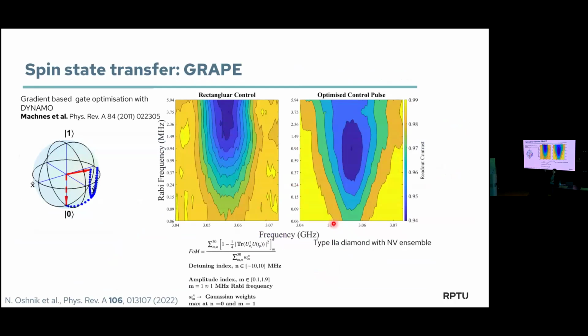So normally you say, okay, I need to get from state 0 to state 1. You can just do a pi pulse, just on your Bloch sphere like this. But now imagine you're scanning your tip, for example, and the microwave field does not everywhere have the same strength. And now your pi pulse is not fitting anymore. So your spin manipulation will not be perfect. You lose sensitivity. And here we have been working on pulses that optimize this.